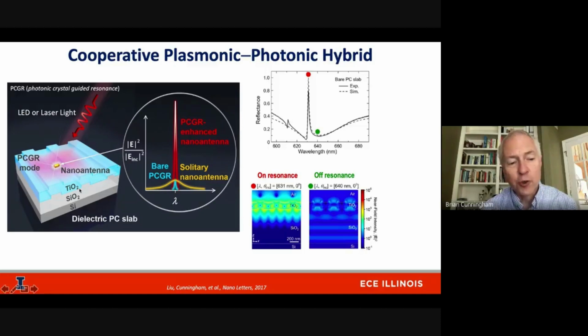What we do is to choose a nanoparticle that has an absorption wavelength that's the same as the resonance wavelength of the photonic crystal. So that if we take that nanoparticle and dunk it into that high electric field region on the photonic crystal, the energy will couple from the photonic crystal into the nano antenna, and that nano antenna will be excited. As I'll show you in just a minute, this effect enables the nano antenna or the nanoparticle to experience much larger, orders of magnitude larger electromagnetic field intensity on its surface than it otherwise would.